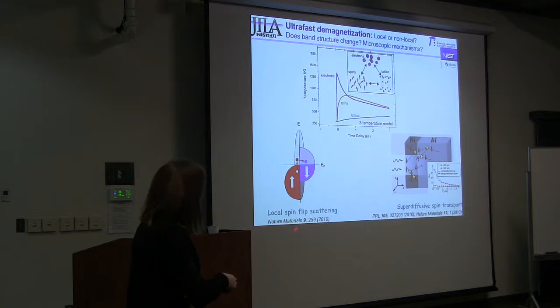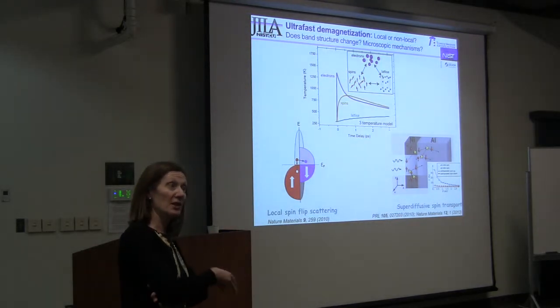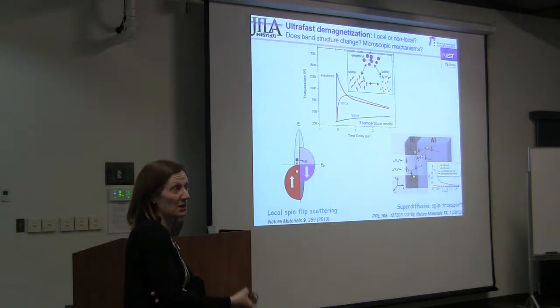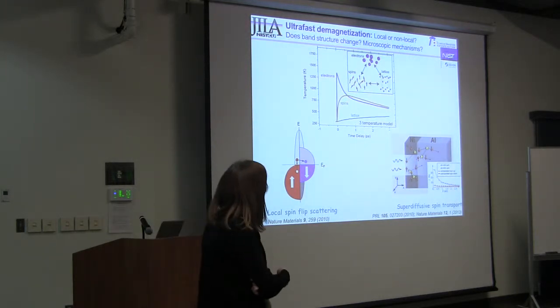The first model was proposed by Bert Koopmans. He said you've got to add in some exchange splitting when you've got a magnetic material. So you heat your electron, the electron scatters with another electron, it can flip its spin, and then cool. Of course, in this situation you are flipping a spin, so this local scattering would give rise to a reduction in the magnetic moment, and you would see the material lose its magnetic state.